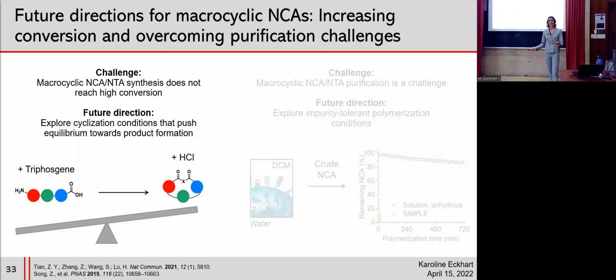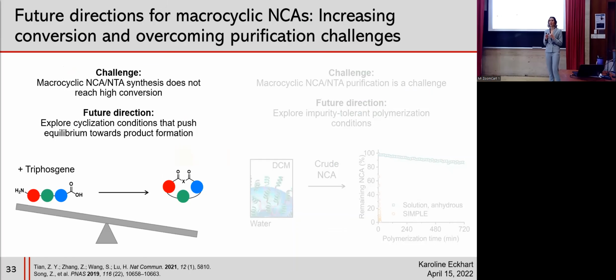So like the last project, there are a couple challenges in this project that we seek to address in the future directions. For one, we weren't able to reach high conversion with either the NCA or the NTA synthesis. So our way to address that is by adding in a scavenger to push the equilibrium towards product formation. For example, in the NCA synthesis, one of our byproducts is HCl. So if we can add in a scavenger that removes that HCl, we may be able to push the equilibrium towards ring closure.